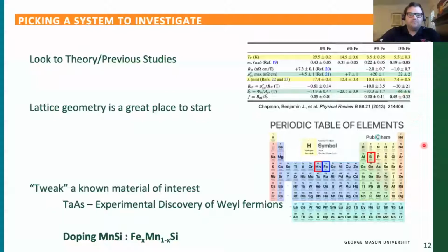This shows doping can be an extremely beneficial process to tune and control the material properties and manipulate them in useful ways. And so, although iron doping here resulted in a suppression of Tc and enhancement of the topological Hall effect, other options like maybe cobalt or chromium may impact the properties more severely or in the opposite way. And there may be plenty of other possibilities and avenues forward.